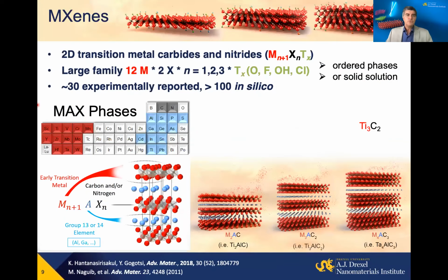Initially, materials were made from so-called MAX phases, which Professor Barsoum at Drexel has been developing, by removing this A element, one of the marked here, the glue, basically. So what is important? We do have layered precursors, and there are many others I don't have time to talk about today, layered carbides, moly two gallium two carbide, another type of structure, not MAX phase here. But the key is that we don't physically delaminate these materials. We chemically etch monolayer, double layer, triple layers of either other metal or carbide out of the structure. So it's a different method, because there are strong bonds in these MAX phases or other carbides between the layers that need to be removed.